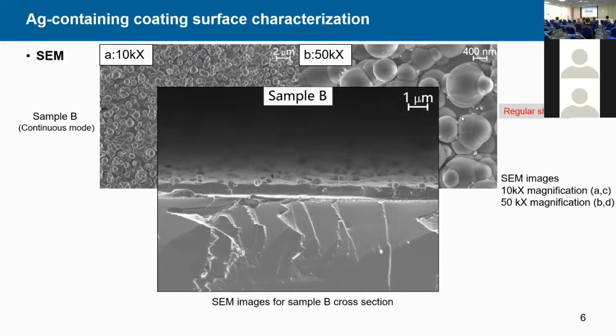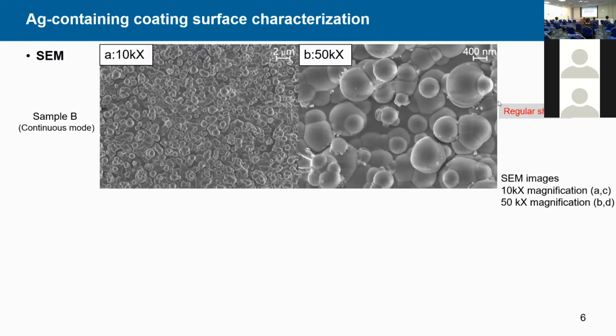Now let's look at sample E treated under pulsed mode. We can notice there are many particles or spheres with smaller irregular shape. That's because in the off time of pulsed mode, the polymerization slows down substantially, while the flow of two aerosols remains unchanged, leading to more irregular deposition.